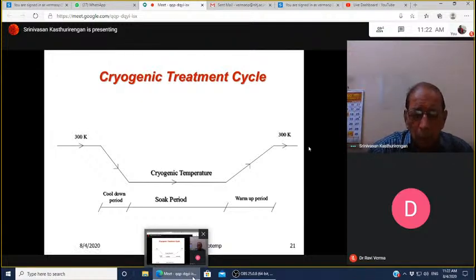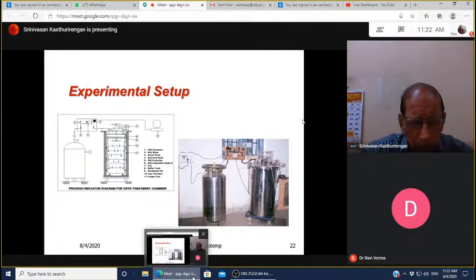Now, this is the experimental setup which Professor Nadik has set up. Now you can see the actual experimental system, and here you have a schematic view. So this is a cryogenic tank which supplies liquid nitrogen to the inside of this vessel, where all the material which has to be cryogenically treated is placed. Nitrogen vapor at different temperatures is allowed to enter this zone, and thereby it gradually cools the samples from room temperature to low temperature, then maintains it at a particular temperature. If you stop your liquid nitrogen flow, then the material is warmed up back to room temperature.